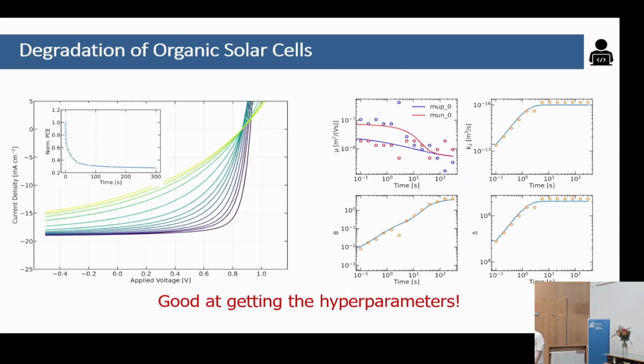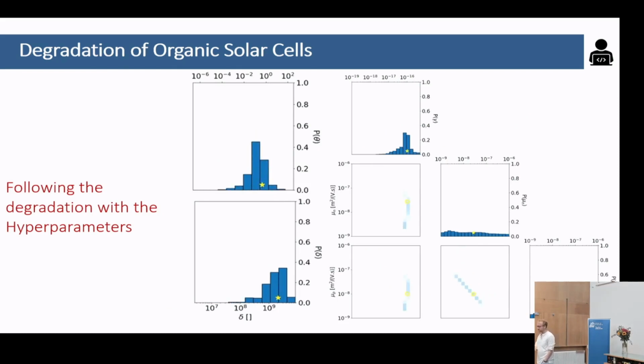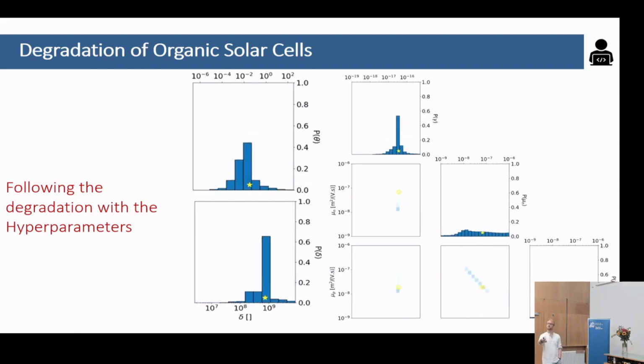Now, this is nice because you can also simulate or even do that on true experimental data. Here I simulated a degradation scenario where the mobilities were going down and the bimolecular recombination strength was going up. And you can make that fit, and you see that getting the mobility right is difficult. Here, actually, you can even see that the electron and hole mobility are completely switched, right? Because I was simulating a very symmetric device, so it makes sense. However, you can get those figures of merit rather nicely, and you can obviously do that even if you have 5, 6, 7, 8 different parameters. And you can also make those kinds of graphs where, throughout the degradation, you can follow how those figures of merit change and see what's happening in your device.